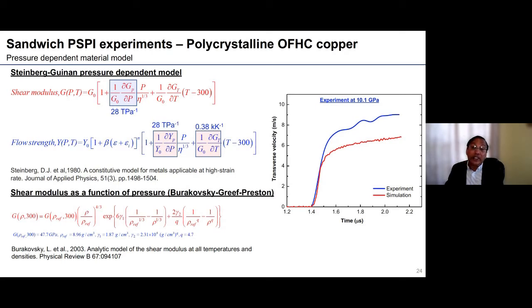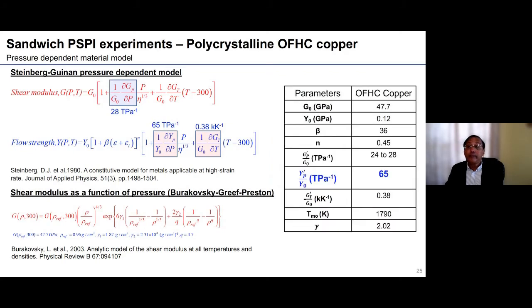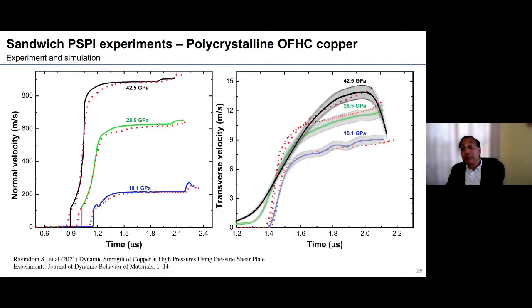So this is why I think the pressure shear plate impact experiment is a very powerful technique. Now, when we don't assume the variations to be the same, we change the variation of the yield strength with pressure to be about 65, which is about 2.6 times the value for the variation of the shear modulus with pressure. Then we see that the results are much better matched.